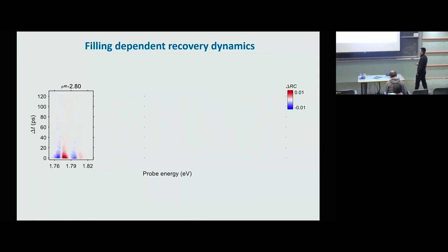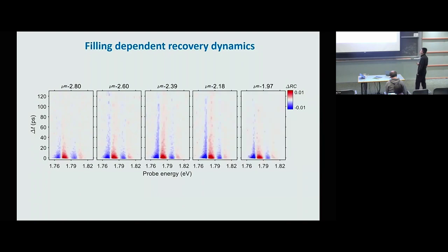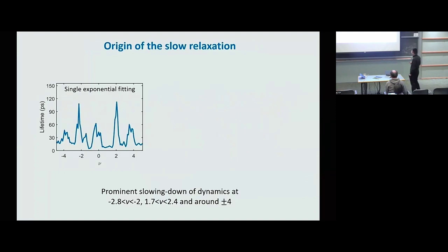We can do the same thing for the hole doping side. Again, this is minus 2.8, 2.6, 2.4, 2.2, and minus 2. Again, we see the dynamics become quite slow over some range, here between minus 2.8 and minus 2. Just to summarize the dynamics, we can do a very crude single exponential fitting to get the filling-dependent dynamics. If we look at this summary, there are a few regions that show slow relaxation: plus minus 4, and also around plus minus 2. Of course, for minus 2, it's not really around minus 2. It's between minus 2 and minus 2.8, away from minus 2 actually, but for simplicity, let me call it around minus 2.